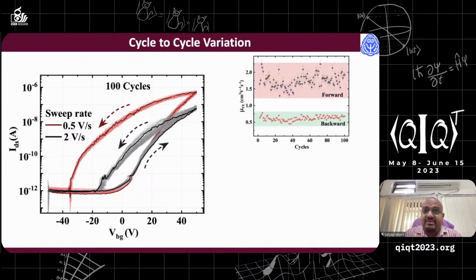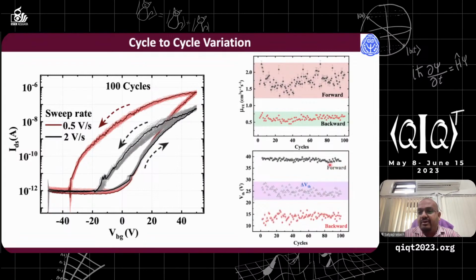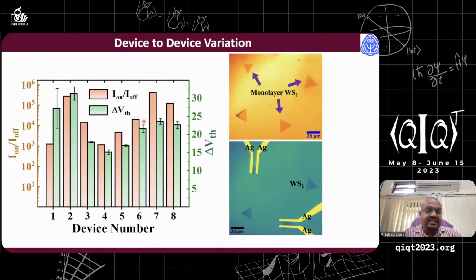And for each cycle, from the forward and backward, we have calculated the mobility, and mobilities are quite consistent. And we have calculated the V threshold for forward, and for the backward, we have calculated the V threshold. These are also quite consistent as seen from this figure. And we have also done device to device variation, which we have done for 8 different devices, and these are quite consistent.